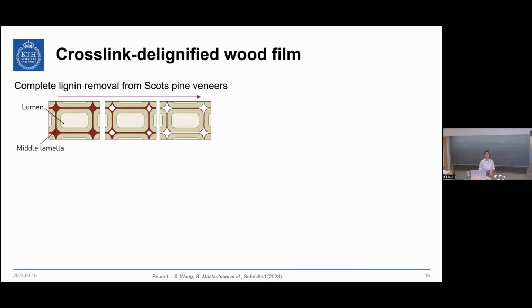To prevent this, what we did was a cross-linking with butanediol diglycidyl ether, which is a common cross-linker used for polysaccharides. It attaches to the OH groups in wood and prevents the loss of cohesion when we remove all the lignin from the structure.